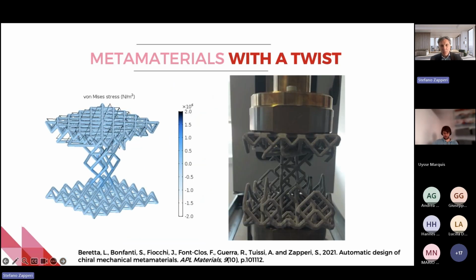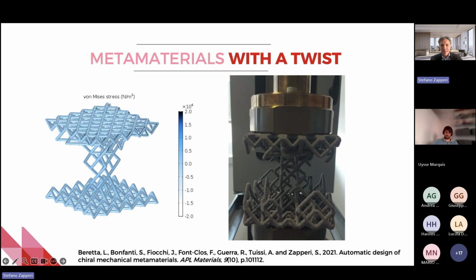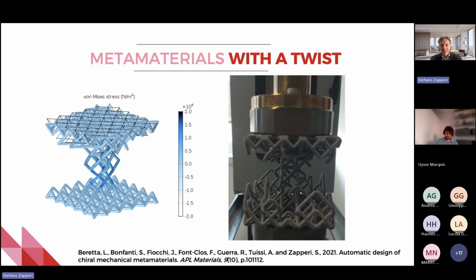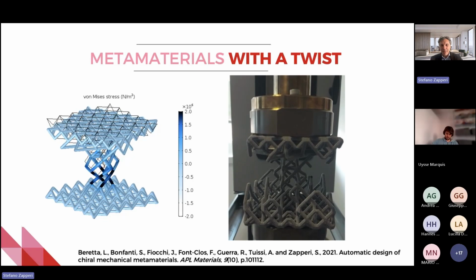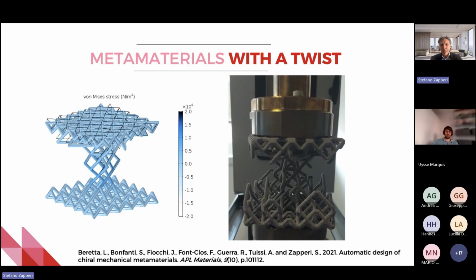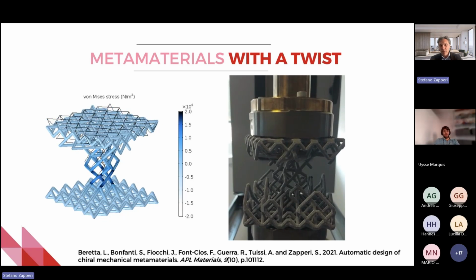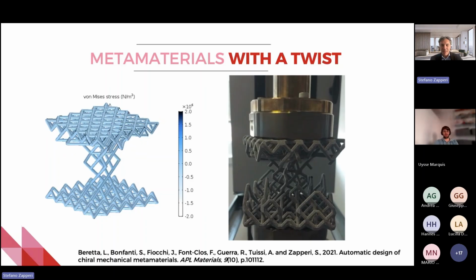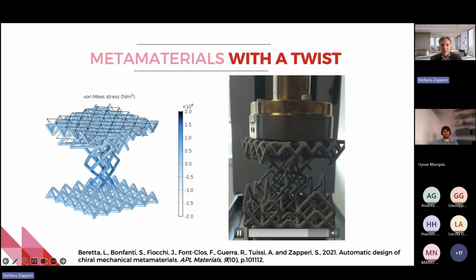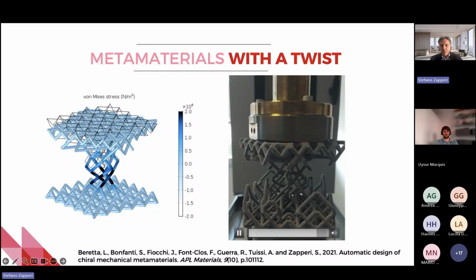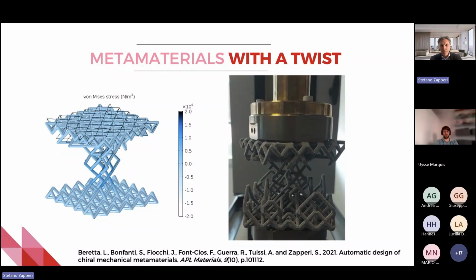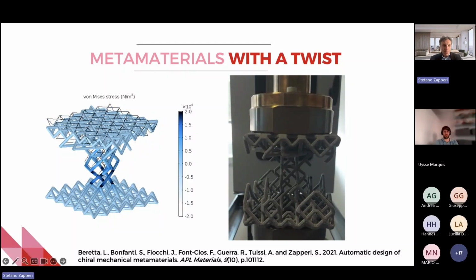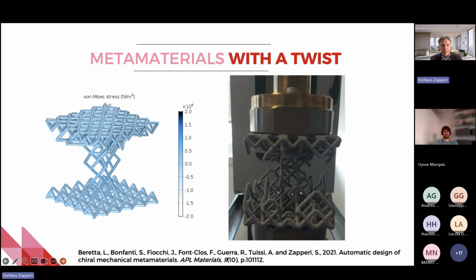And here also we can 3D print and then test that indeed this thing is really twisting. And okay, here it is. It's twisting nicely as predicted. So at the beginning, it's not twisting because the press has to come in contact with the structure. But it's working pretty well. So it works in 2D, it works in 3D.